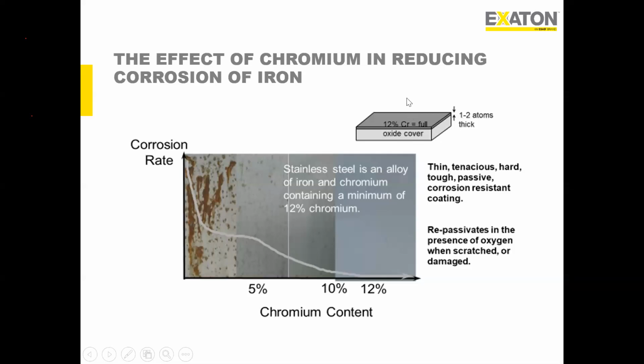You can see on this picture, a 1 to 2 atomic thickness, a very fine layer of chromium oxide forms on the material, and that does not allow the material to react further with the atmosphere. That's how it makes a passive layer, and we get a stainless. So typically we say that for steel to be a stainless, we need a minimum of 12% of chromium, and definitely it could be more. The higher the chromium content, the better the anti-corrosion property.